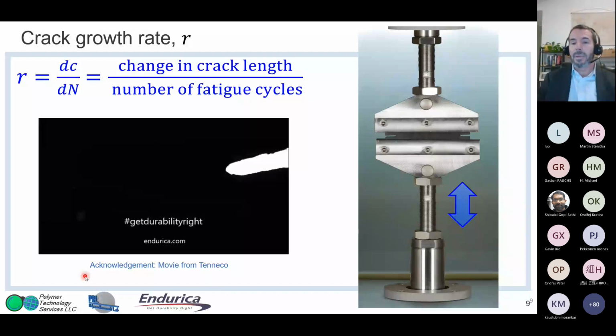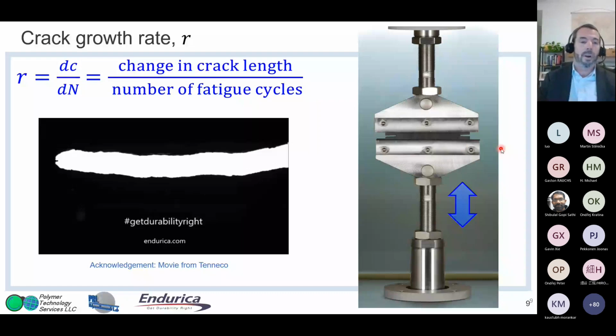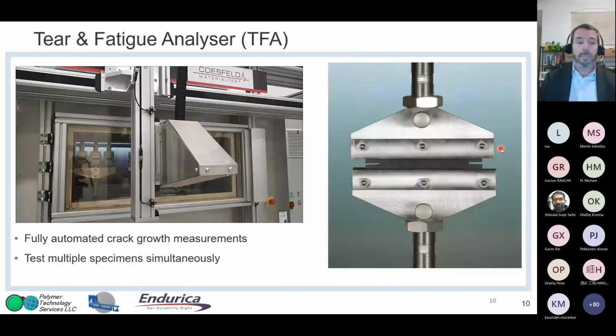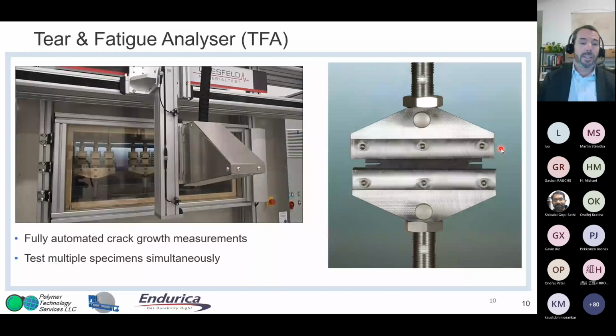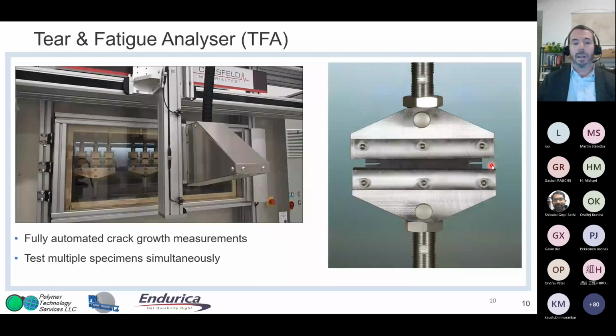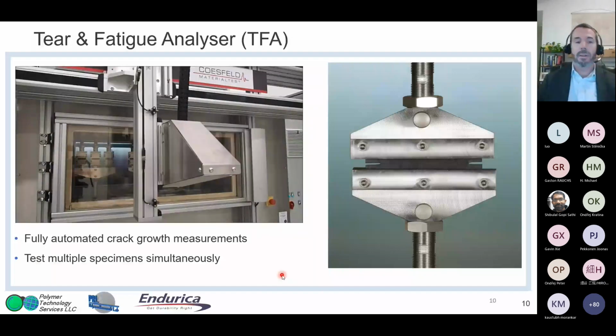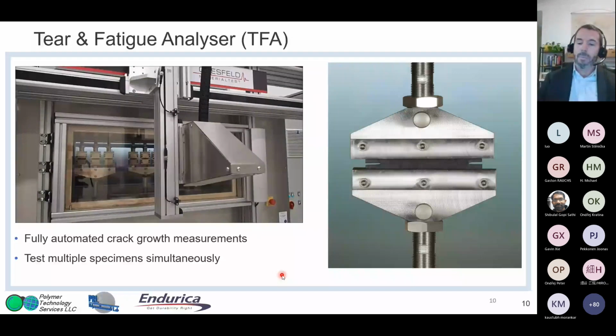And actually, Dr. Stocek, who you'll hear from later, actually pioneered the use of two cracks on one specimen. So basically, it'll allow you to get twice as much information during a measurement. And this can even be fully automated, right? This is a Coesfeld tear and fatigue analyzer. And this particular version is testing 9 specimens simultaneously. There's 3 groups of 3, 3 here, 3, and there's 3 more behind the camera, which is moving. And then each specimen has 2 cracks in it. So you can see the potential exists for really collecting a lot of information about fatigue crack growth in an automated way.